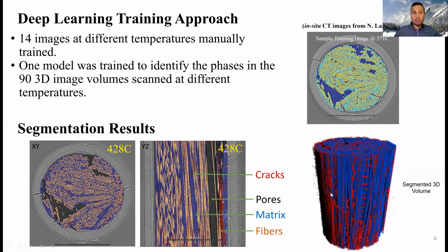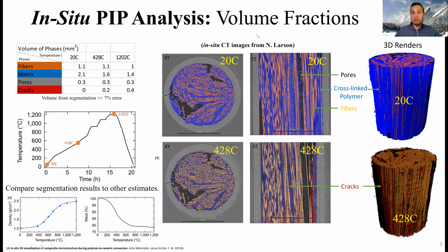A first step that we can do is looking at volume fractions of the different phases, as we've done here for just a sample of 3 different temperatures at 20, 428, and 1200 C. And as you can see here, within the boundaries of error from the segmentation, which could be better, the fibers are more or less the same volume, but the matrix shrinks, as is expected from pyrolysis, and the cracks are growing.